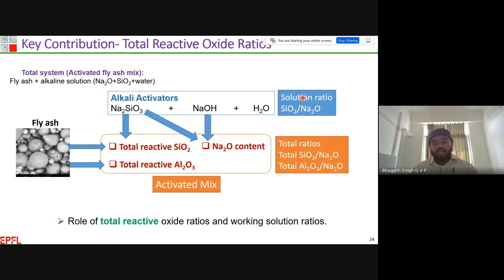And this is the ratio they have been reporting for the past 2 to 3 decades, and whatever ratios have been reported in the literature are applicable only to the type of fly ash they used in the study. If I use the same ratio for another source of fly ash, I will not achieve the same properties as what he has achieved in the study. It is a big drawback in the literature. To address this drawback, I have introduced this total reactive oxide ratios approach.